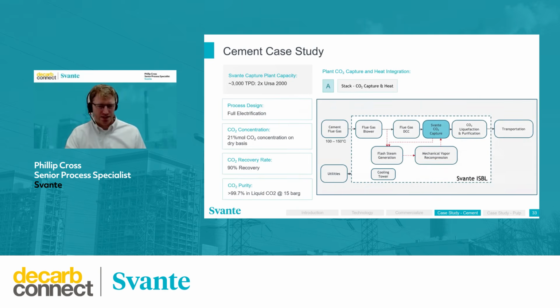So getting a little more into the details of this case study. The flue gas flow rate was 3,000 tons per day. This is roughly 1 million tons per year. This would use 2 of our URSA 2000 units. You can see the design criteria on the left. Of note, 90% recovery. We've also seen studies where we come in and look to do 95% CO2 recovery. Within the ISBL, we have a flue gas blower. We pull a little bit of low-grade heat, and then we send it to a DCC where we do gas cooling. We're then ready to send it into the Svante capture unit.